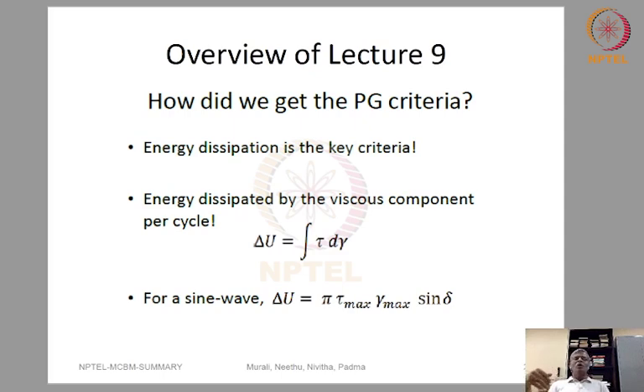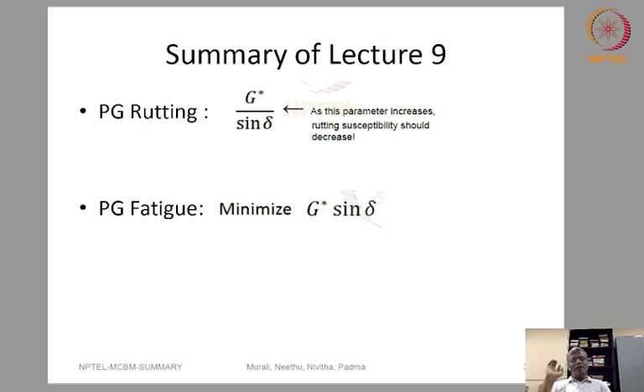If your material is going to dissipate more energy, it means you are going to expect a substantial amount of rutting at high temperature. And the same goes for intermediate temperature also, because fatigue, or the coalescence of micro cracks to form a macro crack, involves energy dissipation. So if the energy dissipation is going to be substantial, you need to understand that there is imminent failure due to fatigue damage. Now, if you really look at the specifications very carefully, there is every possibility for you to get confused.